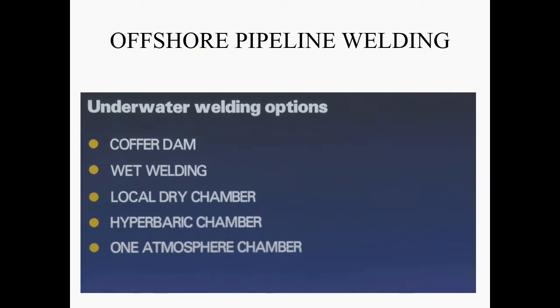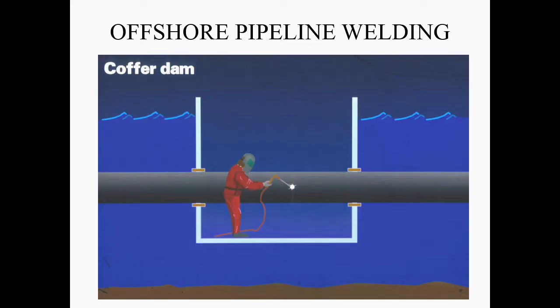the atmospheric pressure. And then a local dry chamber is very similar to wet welding, but we don't protect the welder. The welder still needs to use diving equipment, but the actual welding equipment is encapsulated into something to provide protection. And the others are some special chambers. In one of them, the pressure is atmospheric pressure. That one. And as the name suggests, hyperbaric, because the pressure here is actually higher than the atmospheric pressure. So we'll have a quick look at all of them.